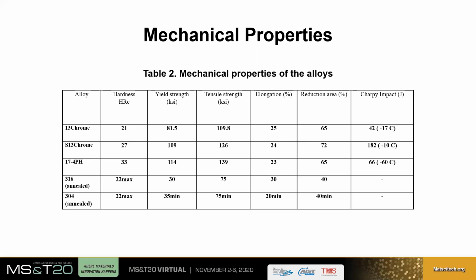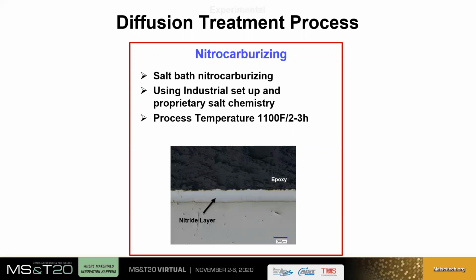So in this study, we subjected these materials to the same kind of treatment, that is nitrocarburizing diffusion treatment, to improve surface properties. Different coupons of these materials were subjected to a salt bath nitrocarburizing process at 1100 degrees Fahrenheit for 2 to 3 hours. We have used an industrial setup to mimic the same condition as done on the parts. So this is kind of different from a lab environment. We have used proprietary salt chemistry to diffuse nitrogen and carbon and form surface nitrides on these materials.